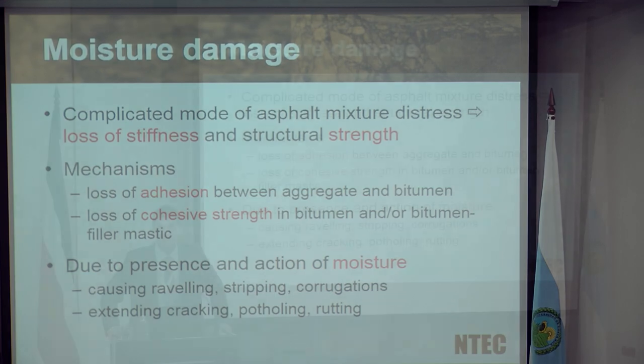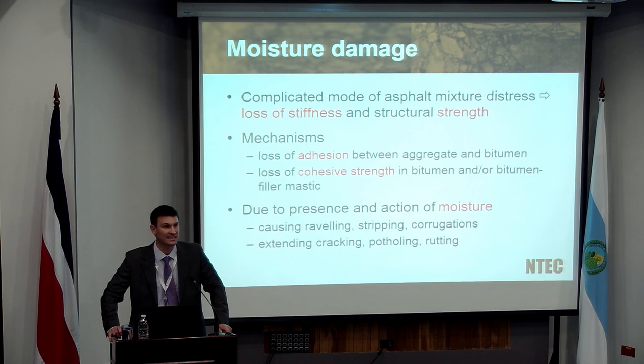We see two different effects. We either see an acceleration of deterioration, so we see more raveling, more stripping of our materials, or we can increase other mechanisms by making them more severe. So if we have moisture damage on a road that is susceptible to rutting, we tend to find that the rutting occurs a lot earlier in the pavement life. If we have an issue to do with fatigue cracking, again, that moisture damage will accelerate the rate of that, in terms of not only the time frames, but also the severity or the degree of moisture damage.